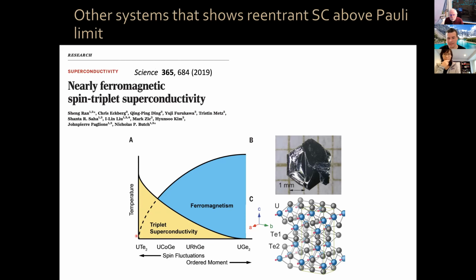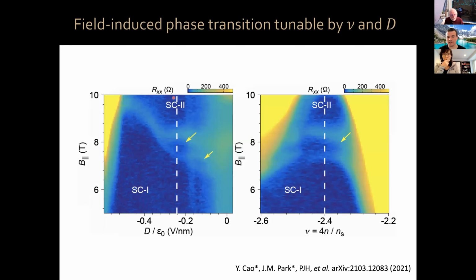Okay. Now, in our system, because again we have many tuning knobs, we can see that indeed there is a field-induced superconducting phase at high field. We can look at this as a function of displacement field near optimal doping, or as a function of filling factor at a given displacement field, shown here, okay? You can see that we have superconducting 1 and superconducting 2 regions. These regions are extended over a range of parameter space. In some cases, we even sometimes see a few extra regions where resistivity doesn't reach 0, so we're not sure if those are fragile superconducting phases or not. But these ones are very robust.